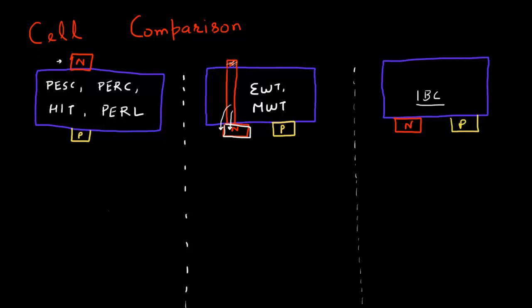So in terms of efficiency, this metal wrap through or emitter wrap through cell, it has higher efficiencies as compared to the conventional cell, but it's lower as compared to the all back contact scheme. So, this efficiency could be, you know, you could get up to a one percentage point increase in your cell efficiency by using this metal wrap through or emitter wrap through design. And most of that increase, it comes from the increase in the short circuit current, because now you have less shading, so you can collect more of these photons coming from the sunlight.